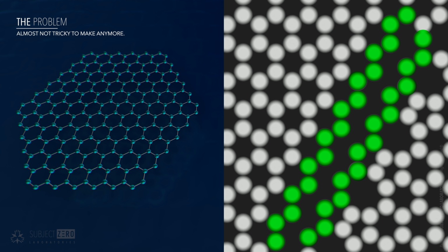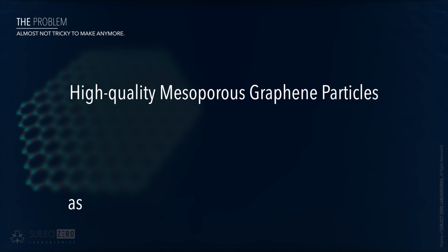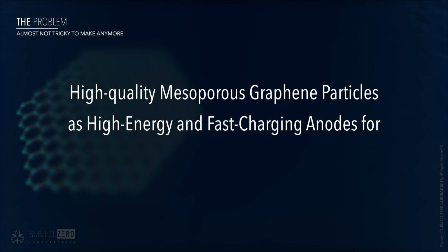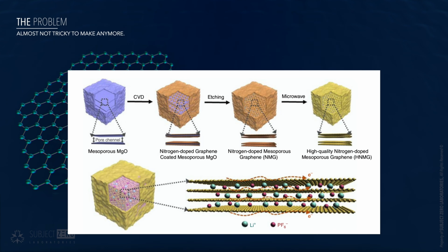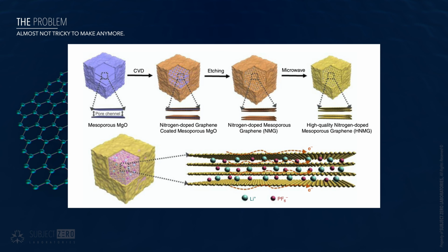But in this research, titled High-Quality Mesoporous Graphene Particles as High Energy and Fast Charging Anodes for Lithium-Ion Batteries, they were able to improve high-quality sheet yield by chemical vapor deposition using a mesoporous magnesium oxide as a template and catalyst to start the process. And then they added an additional step with microwave radiation.